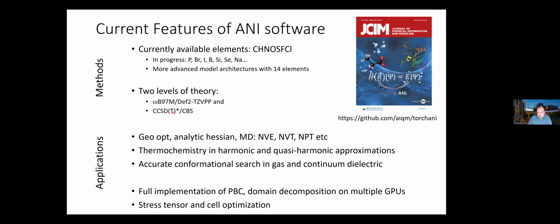So essentially it allows you to do all kinds of typical applications: geometry minimization, properties, molecular dynamics, your favorite ensemble. You can do thermochemistry, harmonic, quasi-harmonic approximations. For molecules, we built tools for conformational search in the gas phase and continuum dielectric for the solvent effect, implementation of periodic boundary conditions, and domain decomposition method. So you can run on multiple GPUs, and analytically compute stress tensors and do optimization of the cells.